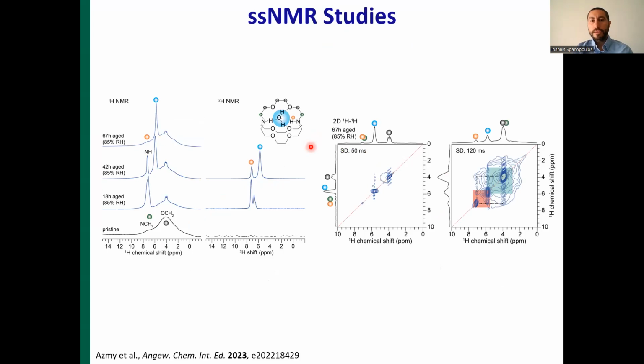In order to shed light on the local structural configuration and identify whether the water and deuterium oxide molecules are indeed adsorbed in the molecular cages, we performed solid-state NMR studies. This is the 1D proton NMR spectrum for the material. In black is the recorded NMR spectrum of the pristine compound. The 2 proton peaks are not resolved, exhibiting the same spectrum as the free cryptand ligands.